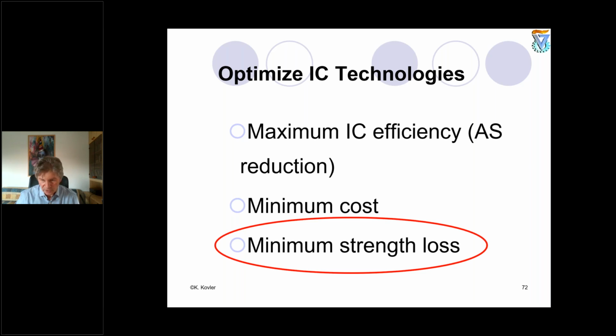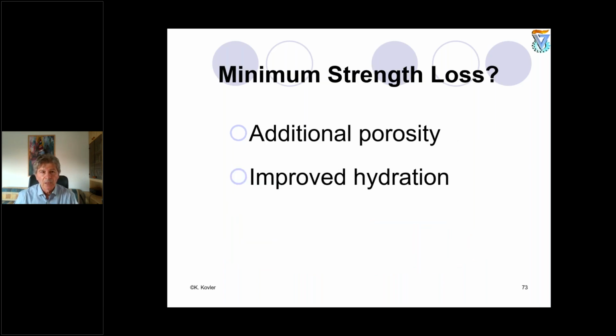So minimum strength loss is a very important topic in many papers, not in many, but in some papers, unfortunately, the researchers put too much agent, and then it resulted in dramatic strength loss. We don't want to compromise all the technology of internal curing. So additional porosity is in trade-off with improved hydration. And we need to understand who wins.